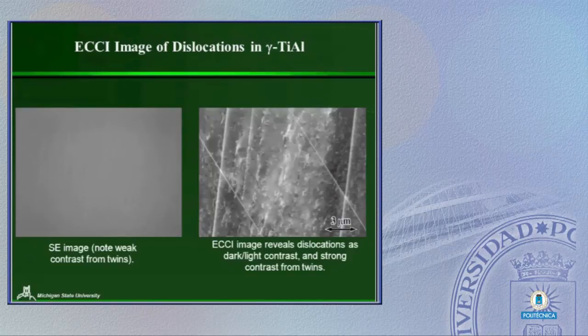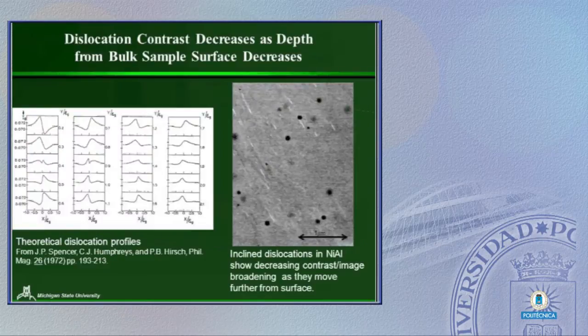And as a result, here's a secondary electron image of a very flat polished surface. But when we image it under the right channeling conditions, if we set up the orientation properly, we can actually see the dislocations in the substructure fairly clearly. Here's a deformation twin, and you can see it sort of peters out here. And these dislocations right through here are the dislocations at the leading edge of that twin. So we can resolve them reasonably well. Maybe not as good as TEM, but not perfect.